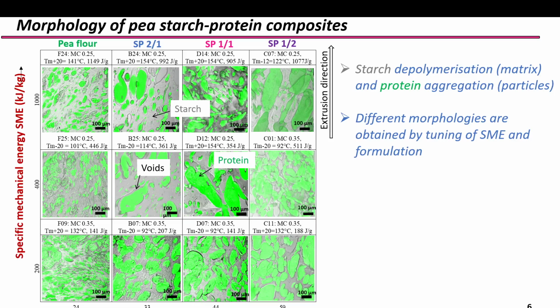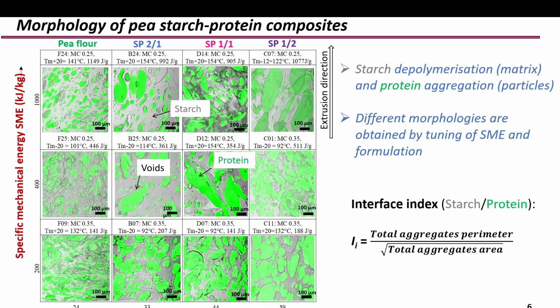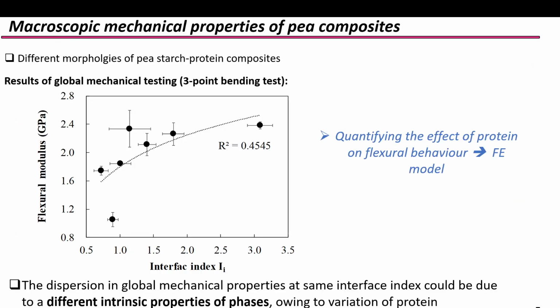In order to further quantify the effect of the process parameters on the morphology of the protein aggregates, we used an index called the interface index. This index is just the ratio between the total aggregate perimeter over the square root of the total aggregate area. We related this index to the macroscopic mechanical behavior of the pea composite. Here is the flexural modulus, for instance, as a function of the interface index, where we see a more or less nonlinear behavior where the flexural modulus increases with the increase of the interface index.